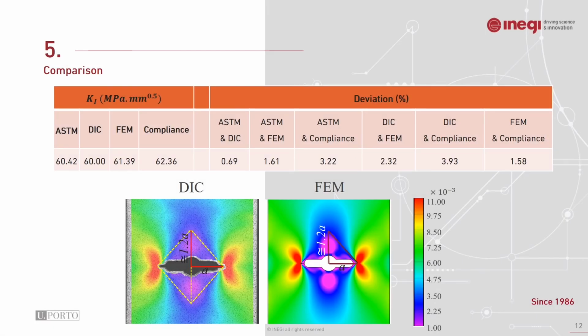In this slide, the comparison amongst the obtained results on the stress intensity factor is presented for ASTM, digital image correlation, finite element method, and compliance function. The table is presented, also the deviation between the studies, and a small deviation of less than 4% was verified.